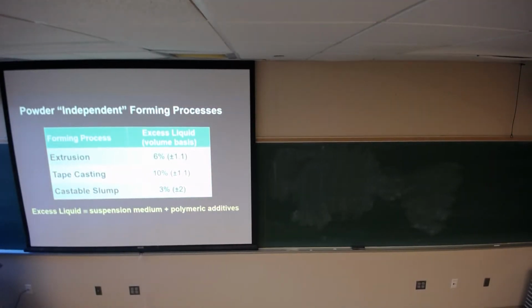So we've defined these process windows. For extrusion, the excess liquid level is 6%, plus or minus 1%. So a plastic body requires 6% excess water. What does that mean? That's the amount of water over the amount necessary to fill the pore space. If I got better packing efficiency and got 60% packing efficiency, that window of 6% is still valid. I need 6% excess liquid in the system to provide room for the particles to move around. Tape casting is 10.